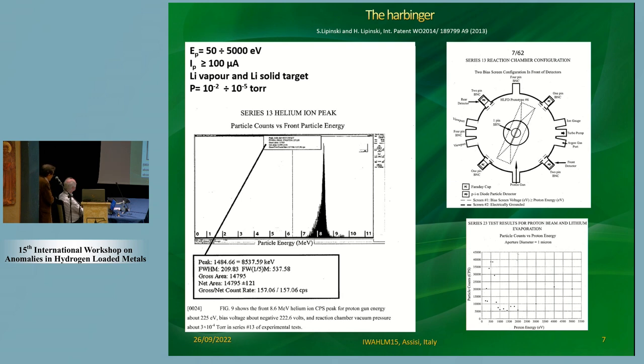And they had a very high counting rate: for a short time interval, they measured a counting rate of the order of 150 particles per second. But they also used lithium vapor, not only a solid lithium target. And even in the lithium vapor, they observed a very large count, of the order of 10,000 up to 40,000 counts per second. This, if confirmed, would be an extraordinary result.